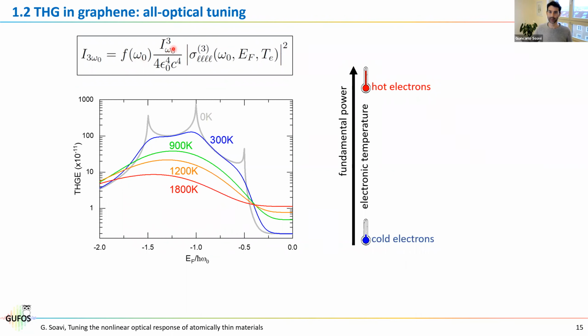Then you have this cubic dependence on the fundamental, and this is what everyone expects from third harmonic generation. So the third harmonic intensity scales with the cube of the fundamental intensity. Here again, we have some constant, and then we have this σ3. Now, σ3 is the third order optical conductivity, which is basically proportional, just out of phase, to the susceptibility, the χ3 terms that I was mentioning before. We typically use the conductivity here because the conductivity is well defined in 2 dimensions, while the susceptibility, the χ3, is not well defined in 2 dimensions because this involves the propagation inside the material. And as I was saying, this doesn't make a lot of sense in 2D materials.